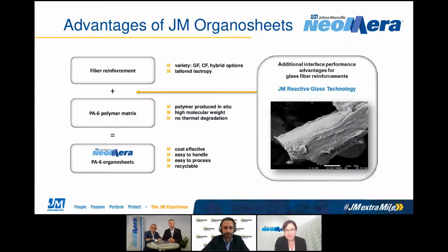And what we really like to talk about when it comes to glass is an added advantage that we have as a glass manufacturer. For glass fiber reinforced organosheets, JM is using fibers that are made with JM reactive glass technology. That's a proprietary sizing that allows the polymerization reaction to start from the glass surface, so that at the interface between the glass and the polymer, there is a strong covalent bond that leads to additional advantages, better shear strengths, and ultimately helps with those fatigue cycles. Those are the advantages that come from components.